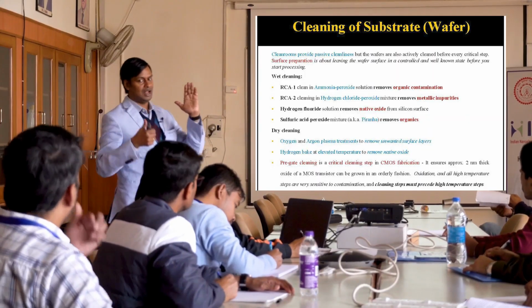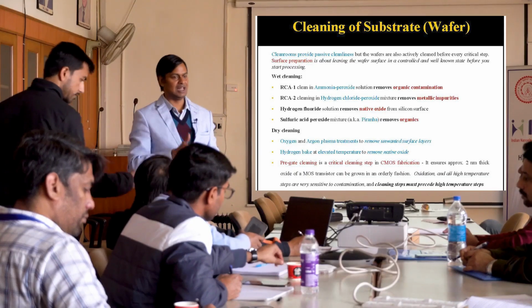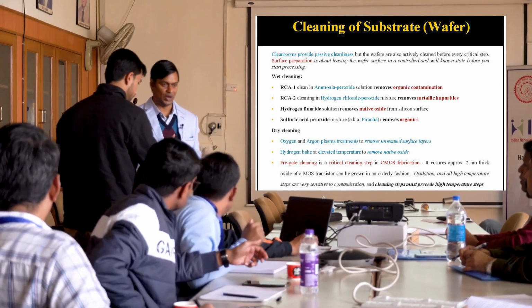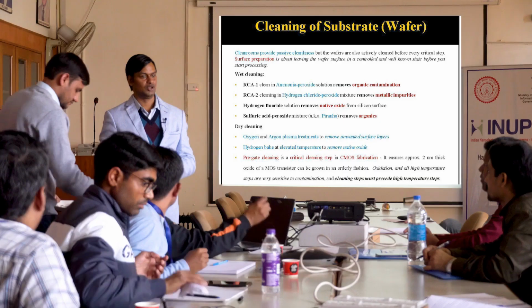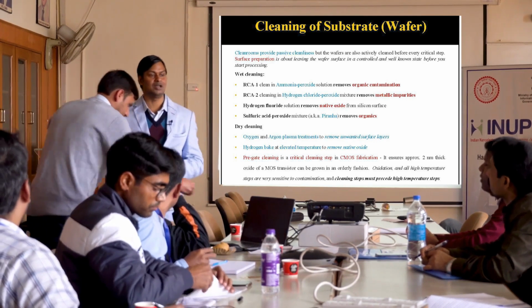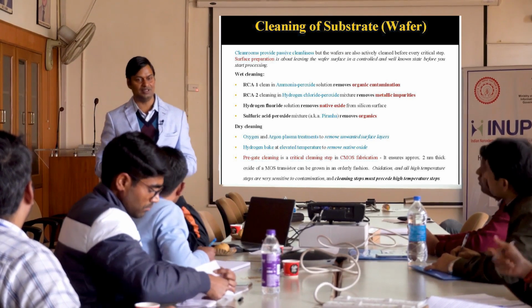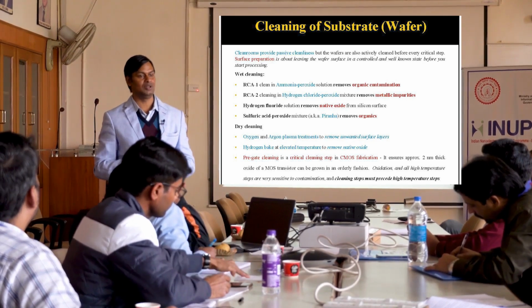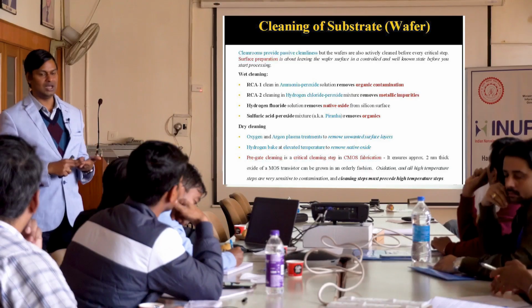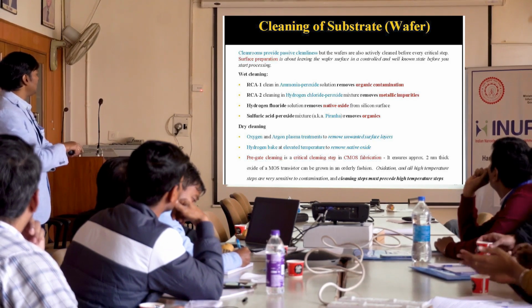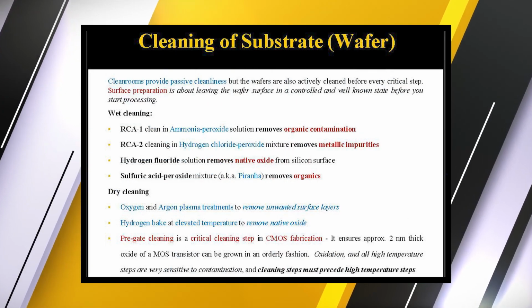For example, there is a silicon wafer and accidentally you have touched it with your finger. What does the thumb impression actually contain? What are the chemicals which you can transfer in your thumb impression? Dead cells, skin cells, then sweat. What are the constituents of sweat? Sodium. Sodium is the most potent contaminant for any semiconductor device. If you have sodium contamination on any of the surfaces, you have to get rid of it by etching it with hydrofluoric acid. So obviously you cannot touch any silicon wafer by hand, but somehow if you do, you have to follow all these steps: RCA1 cleaning, followed by RCA2 cleaning, then piranha cleaning, and then finally an HF dip. RCA1 cleaning removes organic contamination and RCA2 cleaning removes metallic impurities.